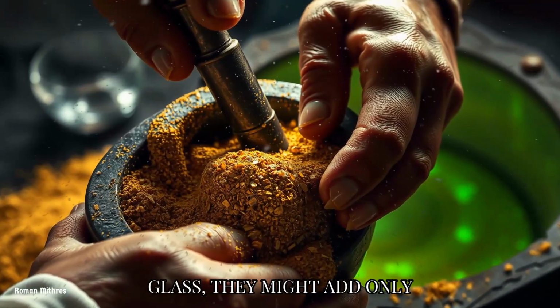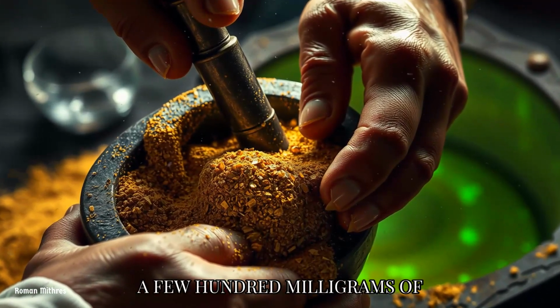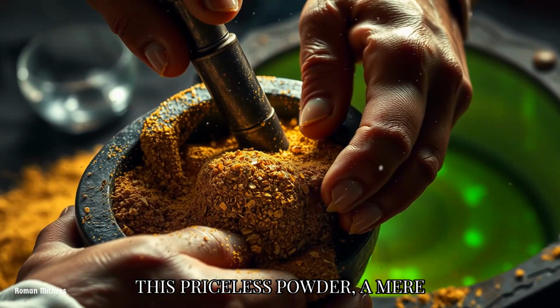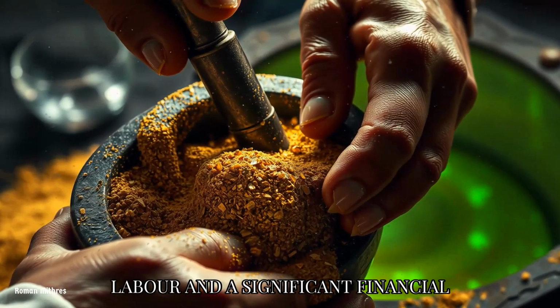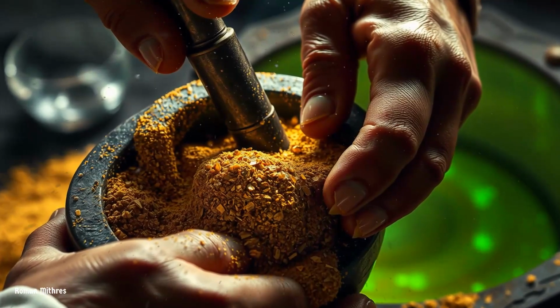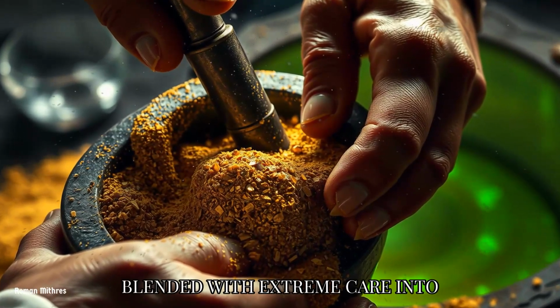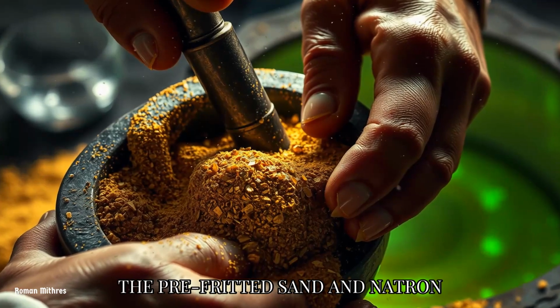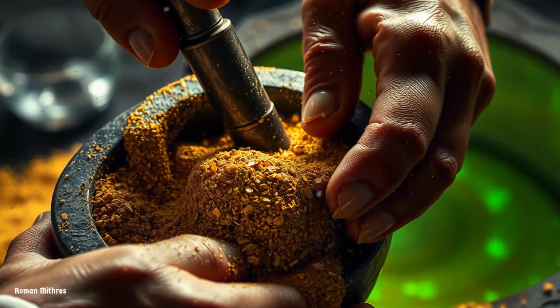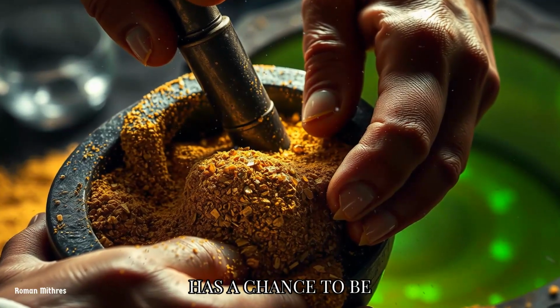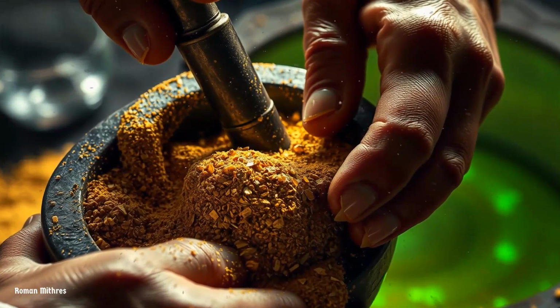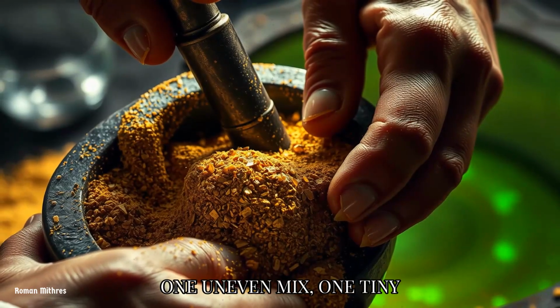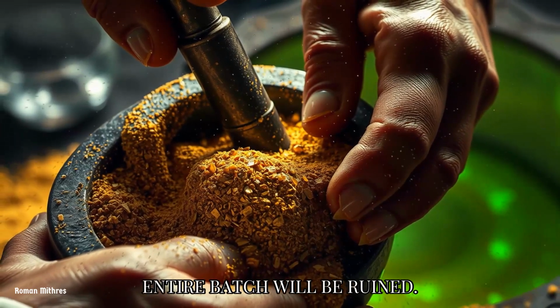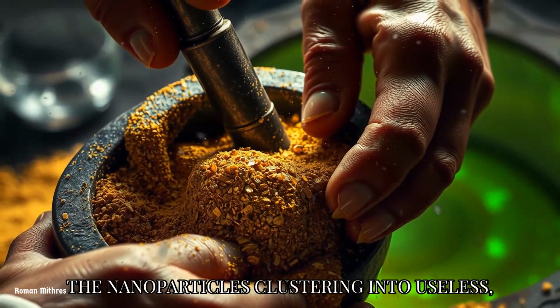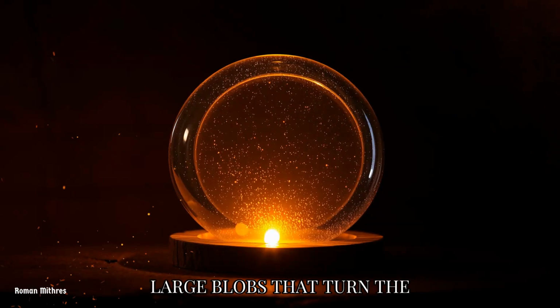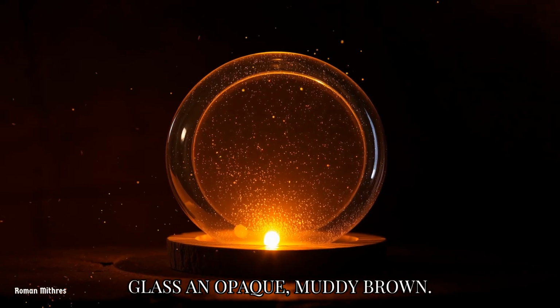For an entire batch of glass, they might add only a few hundred milligrams of this priceless powder, a mere pinch that represents weeks of labor and a significant financial investment. This minuscule amount is then blended with extreme care into the pre-fritted sand and natron mixture, ensuring every grain of sand has a chance to be touched by a particle of metal. One uneven mix, one tiny clump of alloy, and the entire batch will be ruined, the nanoparticles clustering into useless, large blobs that turn the glass an opaque, muddy brown.